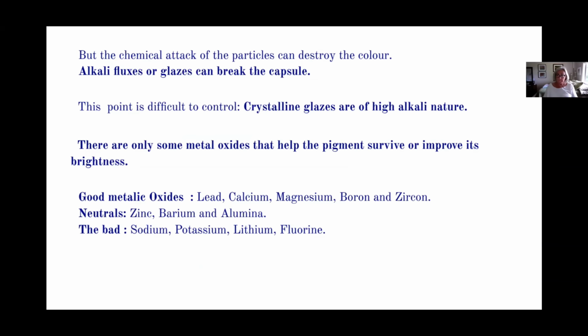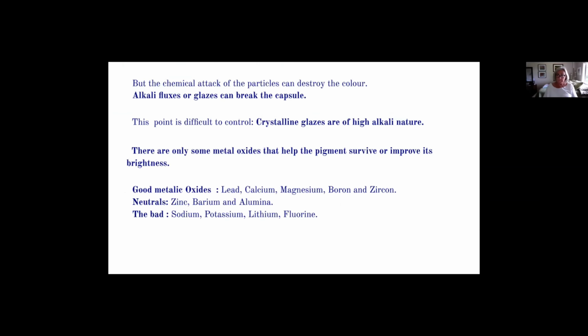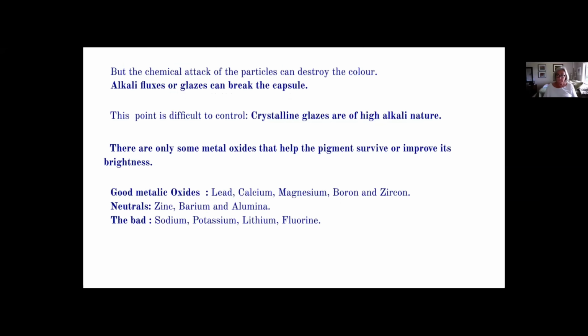You need 3. There are only some metal oxides that help the pigment survive or improve its brightness. Good metallic oxides are lead, calcium, magnesium, boron, and zircon. Neutrals are zinc, barium, and alumina. And the bad ones are sodium, potassium, lithium, and fluoride. On the first or second day we talked about how you need frit with sodium to make crystalline, but now we are saying it is bad for getting reds. That's why you need 3 layers.